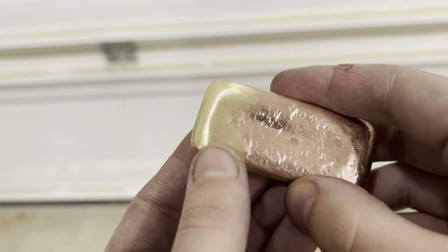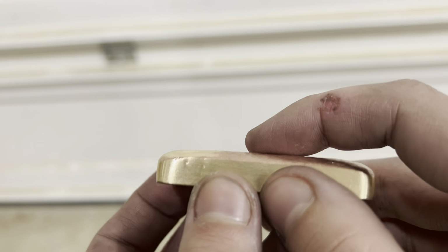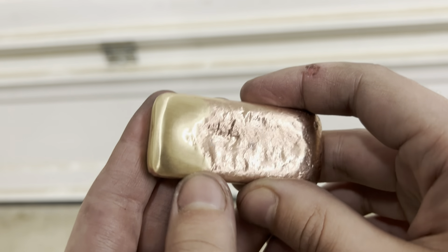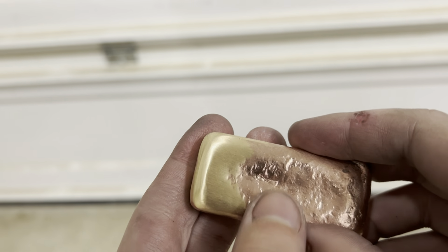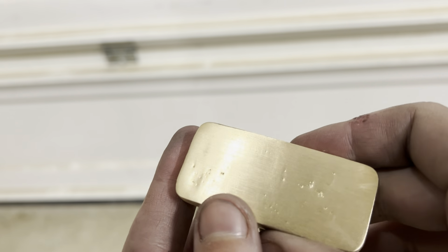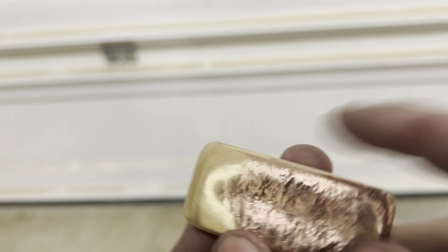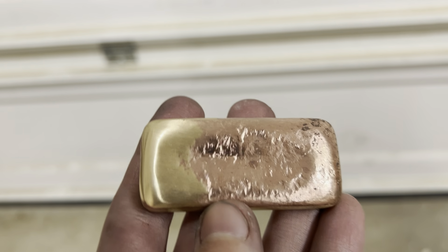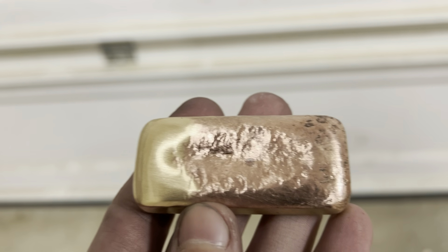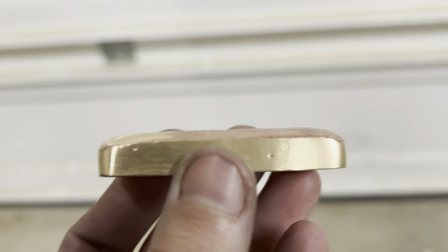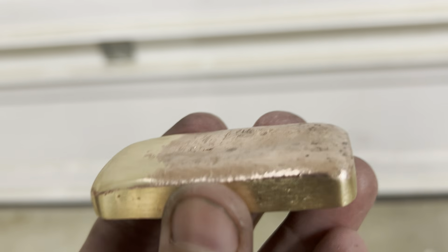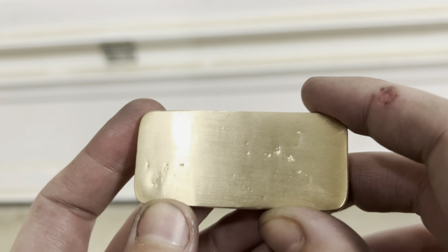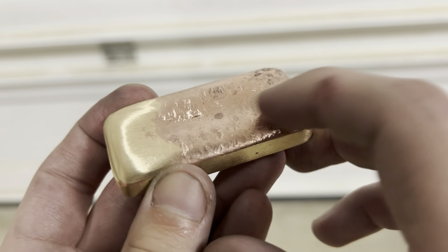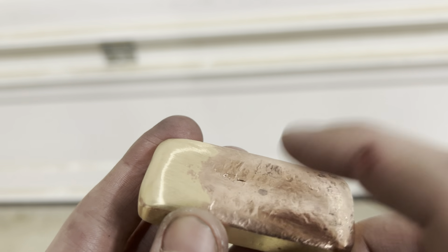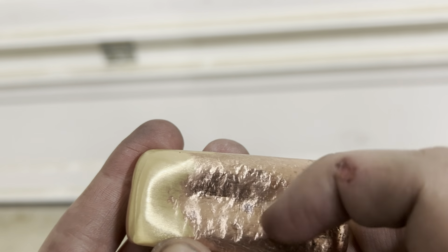And to show off this kind of interesting skin that the tops of the ingots get, I took the flapper disc and sanded away part of it to reveal that the rest of the bar, despite this cool surface effect, is that same uniform, nice pale golden color. So as I was saying before, this is an alloy called New Gold. In industry, it's alloy C23000. It's a type of what we call red brass, because it doesn't have as much zinc as some of the yellow brasses, and it has more of this kind of reddish golden tone. And I also noticed that whenever I cast red brasses, all of them get this kind of red effect on the top.